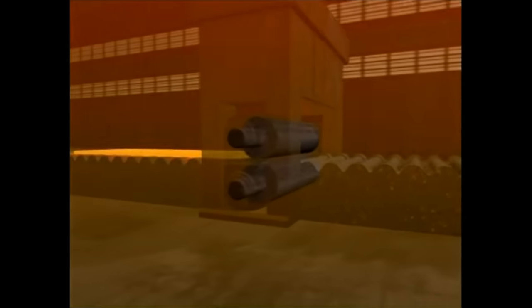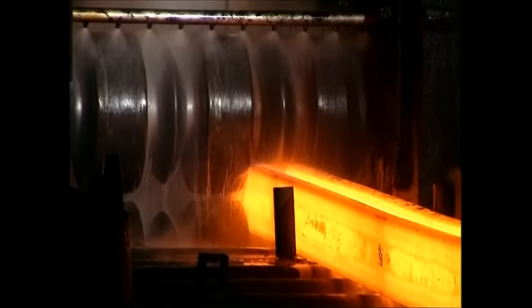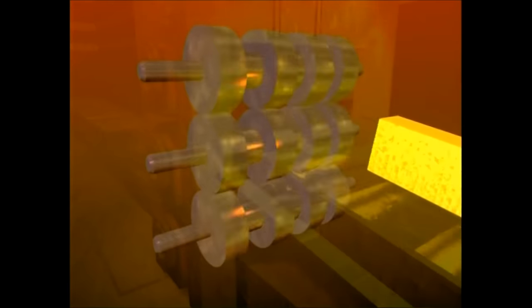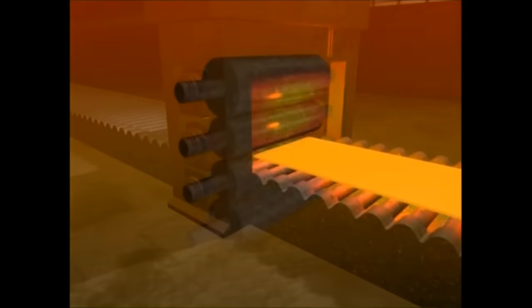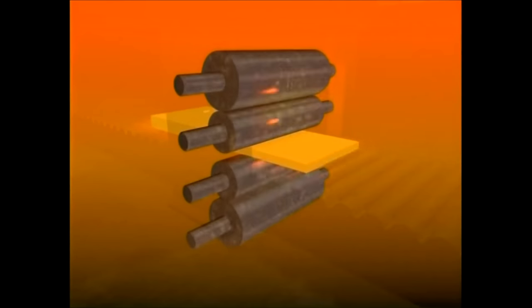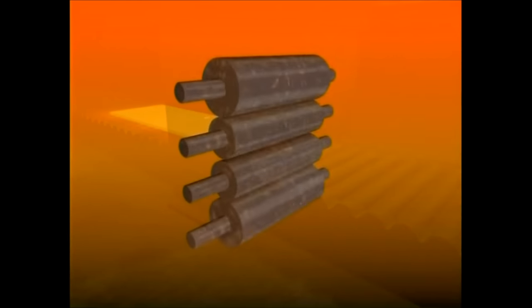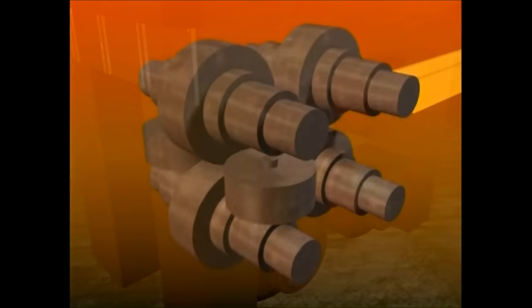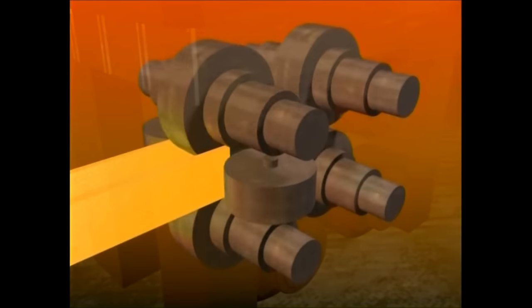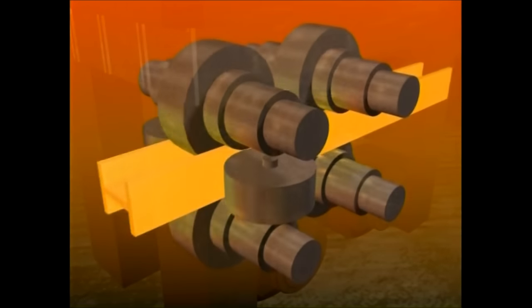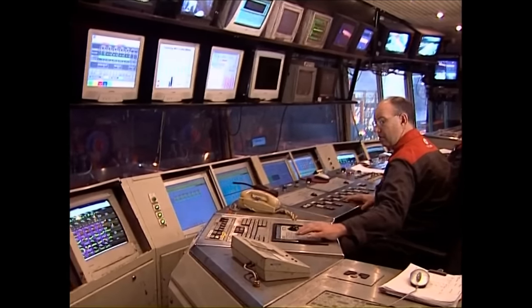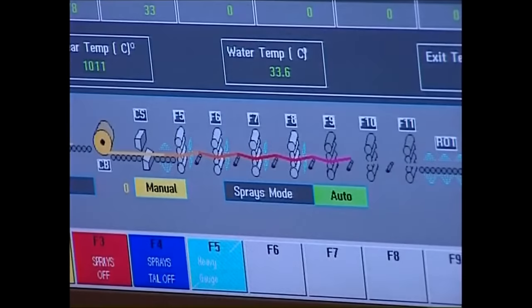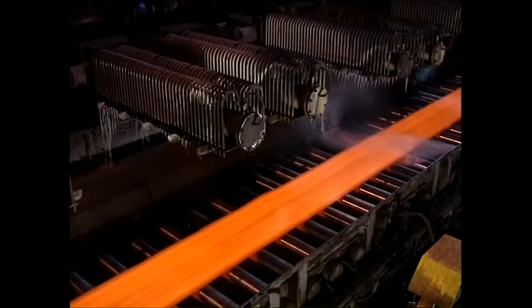Mill stands have various roll arrangements depending on what product is being rolled. The simplest arrangement is a two-high stand, and these are mainly used for long products such as sections, piling, rails and rod rolling. For light sections and bars, three-high stands are sometimes used, with the steel passing one way through the back through the top gap. Four-high stands have two work rolls in contact with the steel, supported by larger backup rolls to prevent distortion caused by the rolling face. These give greater accuracy for rolling flat products. Universal beam mills also include stands with both horizontal and vertical rolls bearing on the steel simultaneously. Rolling processes are computer controlled, monitored up to 50 times per second and measured to an accuracy of plus or minus 50 microns.